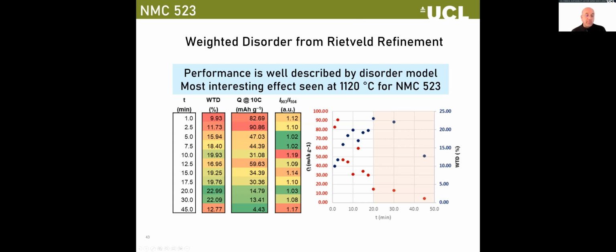So what we've plotted here is capacity values, and this is at 10C. So this is a 6-minute charge or discharge. Anything near 100 is very, very good. So that's the capacity values in red. The blue is the total weighted disorder as calculated, as I described earlier. In this column, we can see the capacity and we can see the weighted disorder.